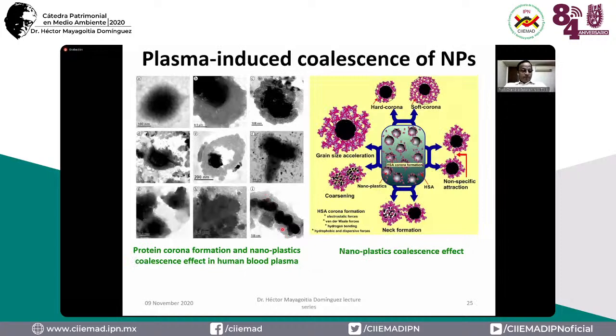Once again, this is protein corona formation and nanoplastic coalescence in human blood plasma. That was human serum albumin. This is the case of blood plasma, showing how the corona formation, neck formation and coalescence of these particles take place. This is the coalescence effect, hard corona, soft corona, the grain-size acceleration, and this is non-specific attraction. This is the nanoplastics, and this is the coarsening of the nanoplastic with the protein molecule, and there's a neck formation.